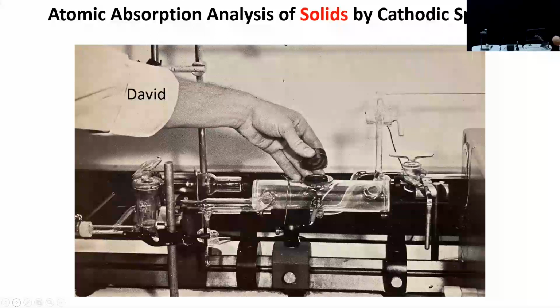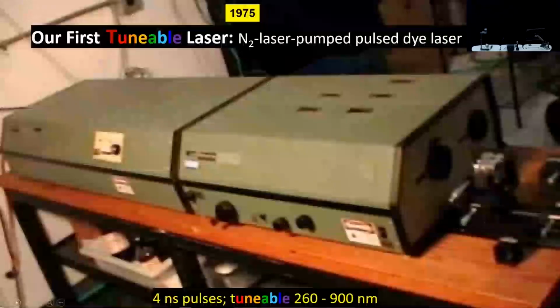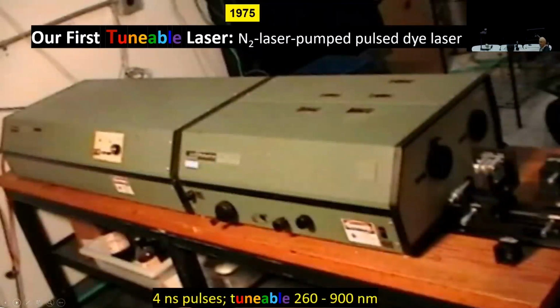And we looked into producing an instrument that you can just put the sample on top, a solid sample, might be an alloy, and you measure the absorption from this hollow cathode lamp. It worked nicely. We had it commercialized, and people in Analyte Corporation in Oregon engineered it to make it look fancy and work very nicely, and sold these off. Unfortunately, it didn't really take off because the flame was still very, very popular. And so we thought, okay, lasers have now come on the scene, so let's use this method of vaporization to do laser spectroscopy, essentially any element in the periodic table. So this is our first tunable dye laser, which was pumped by a nitrogen laser. It had 4 nanosecond pulses, and you could tune anywhere from about 260 to 900 nanometers over a very broad range.